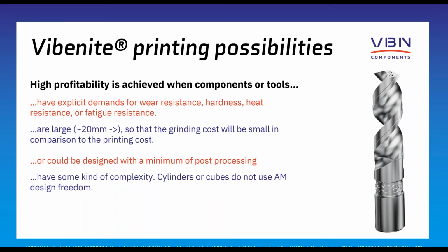Of course, we can produce cubes or cylinders directly, but if we do that, then you do not use the freedom you have with additive manufacturing technology. Of course, we can do a test cube, which you typically do also. But really, to benefit from this technology, you need the complexity. And you need to use that complexity for a better performance in your end application. Today, we have a limitation in build volume, which is typically about 230 times 230 times 350 millimeters. And this is a machine parameter, what we have today. And the price, of course, is set by a serial size.